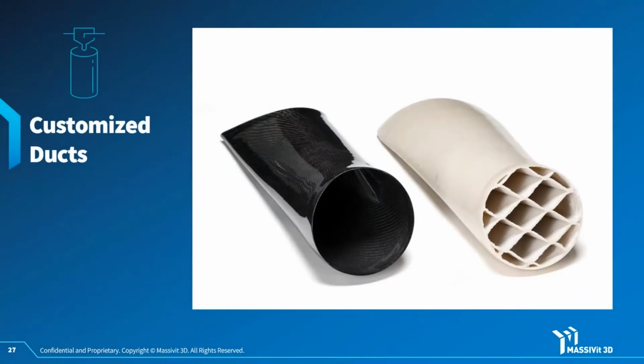Here's another example. We have an aerospace customer that needed a washout mandrel. The challenge here was, how do you get this core or this mold out of an odd-shaped part, like ductwork? On the right, what you see is the 3D printed soluble material as printed, no epoxy, just the 3D printed material. Then they make the part on the mandrel. And when the part is fully cured, you can soak it in the water and remove the mandrel from the part.